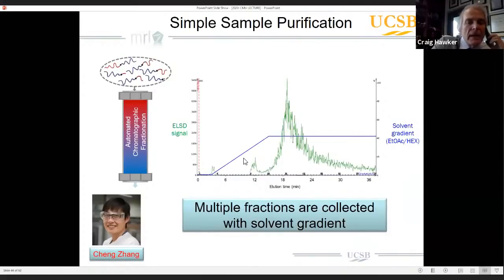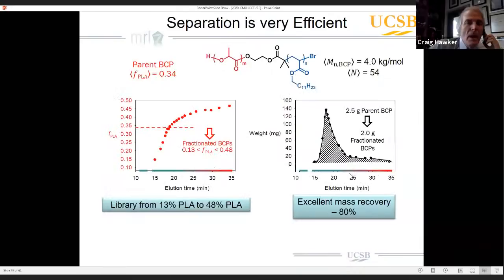The first thing I want to go through is that in all of the samples that we look at, we tend to find an initial peak, which is one of the homopolymers. So not only do we start to fractionate this material, but we actually make this material much purer than the starting diblock copolymer system. It's really easy to get rid of the starting homopolymers in these samples. Again, you use your solvent gradient and you start collecting multiple fractions as you increase, in this case, the amount of ethyl acetate in hexane. And you see what happens. Here we have our parent diblock copolymer. The fraction of lactide is 34%. If we look at the elution fractions or time, you can see that we're starting to get diblock copolymers that have very low amounts of lactide.